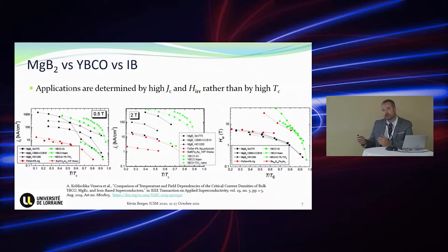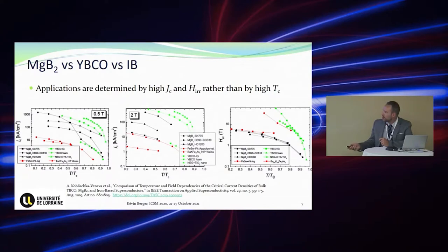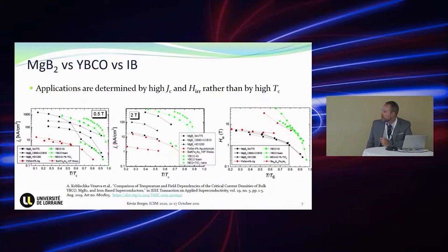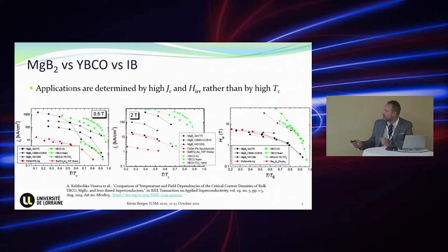If you remove the problem of temperature, you can plot and compare the materials on a reduced temperature scale. This is not often done, but we did it for comparison purposes. We compared MgB2 (the black curve), YBCO by infiltration growth, YBCO foam, and iron-based superconductors. When plotted against reduced temperature, YBCO at low field — even 2 T background — still has better performance than the others, but MgB2 is still a good challenger. This is why we are now focusing on MgB2's potential for applications.